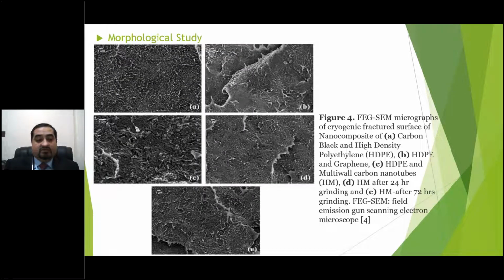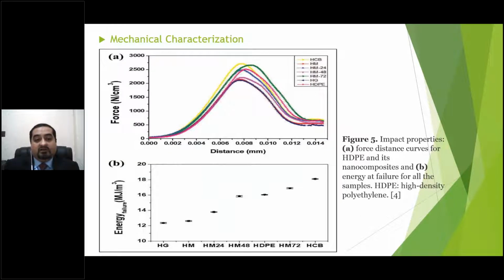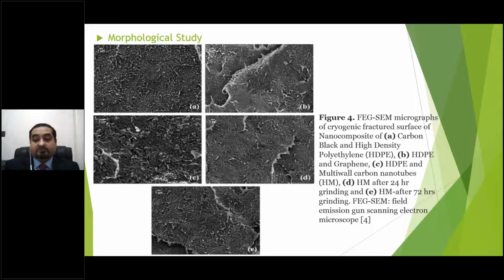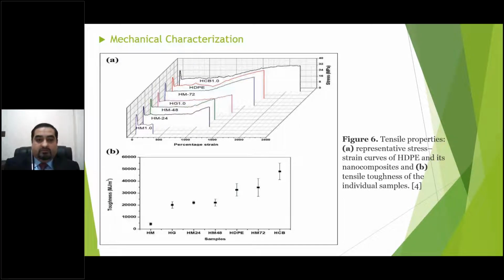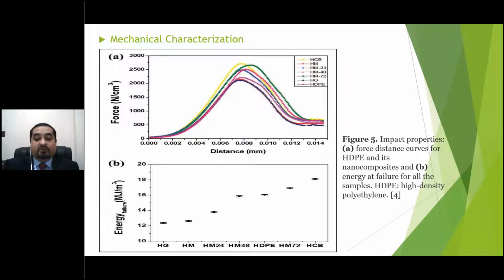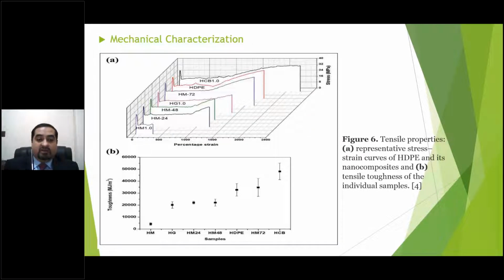This is the SEM picture in which you can see very few agglomerates have formed, and a uniform dispersion and distribution of the carbon black, the graphene, and multi-wall carbon nanotube is visible from the field emission gun scanning electron microscope results. We started doing the mechanical characterization of these specimens, and the impact properties showed an enhancement in the properties of carbon black based material in comparison to the other materials that we incorporated. So this basically gave us a heads up that these materials can be incorporated to produce polymers with enhanced properties. The mechanical characterization showed the same results.